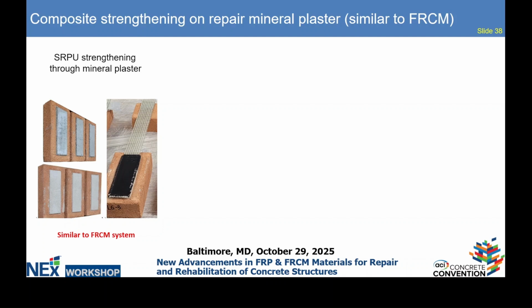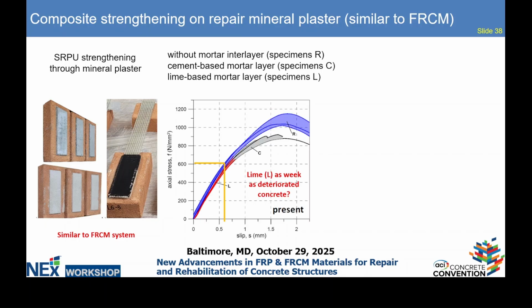So coming to the FRCM system. FRCM system, as Cristiano said, is the sandwich of fibers and mortar, yeah? In this sense, we used mortar only at the bottom, and we bonded at the top with polyurethane flexible matrix. The blue one is when we don't use the mortar. The C is when we use cementitious mortar. L is when we use lime mortar.